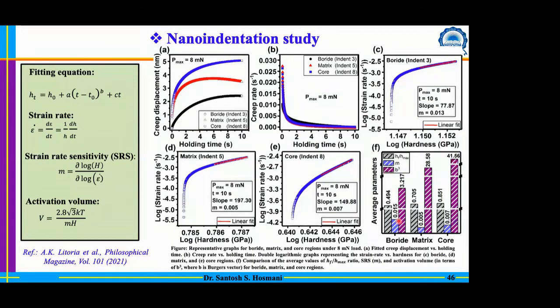Now, another piece of information we can get from the nano indentation is the strain rate sensitivity. It is a very crucial factor. For strain rate sensitivity, you can look at the bar figure, figure F. Here you can see the m value, the blue one. This strain rate sensitivity is the highest, even higher than the matrix and the core. That is good information.